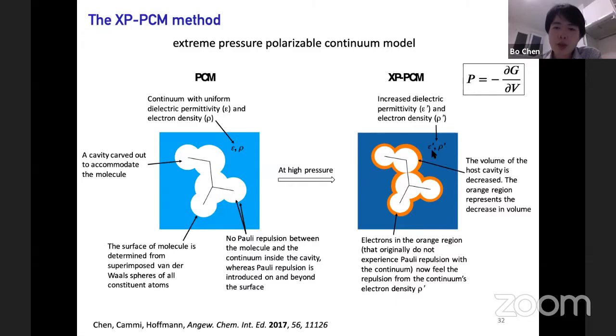And at the same time, we increase the electron density of the medium, and that leads to an even stronger Pauli repulsion with the molecule. So an increase in the Pauli repulsion, in my view, is sort of like the microscopic response to an increase in pressure. In the actual calculation, we need to calculate the energy of the system at different volumes, then we plot the energy versus volume, and the pressure comes out as the negative of the slope of that curve. I hope this makes sense.